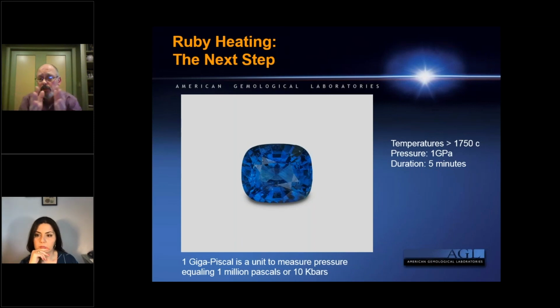Some laboratories disclose it just together with the more commercial heating. Labs such as ourselves and GRS, we've taken a more conservative approach in the beginning, where when we can detect that a stone is heated with pressure, we disclose it. And it's because, from my standpoint, we're still at the early threshold of this. So we don't really know what's going to come afterwards. And so I prefer to take a more conservative approach on disclosure of this material.